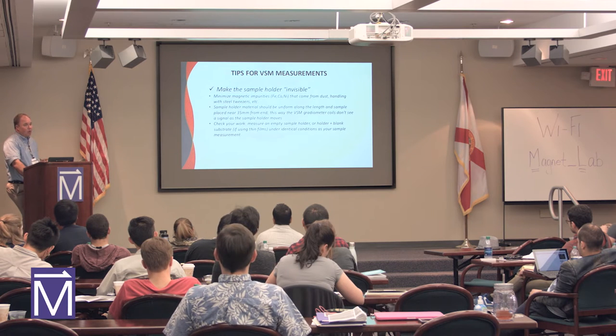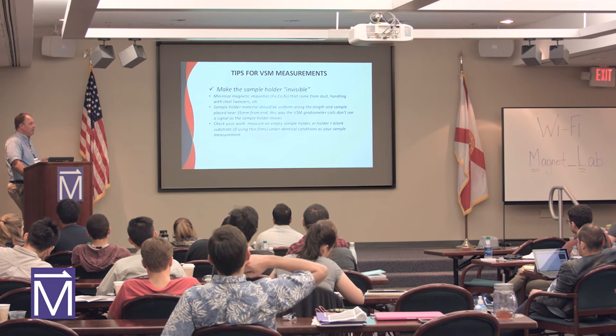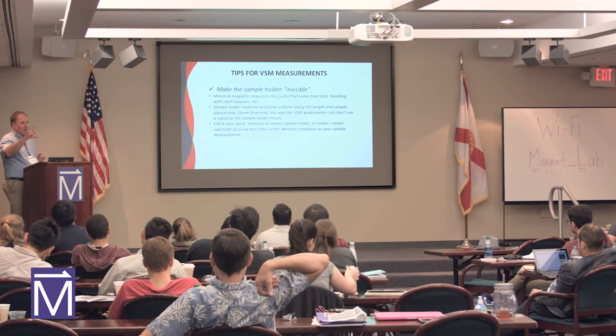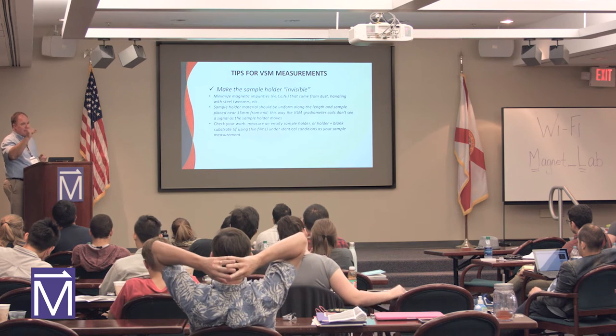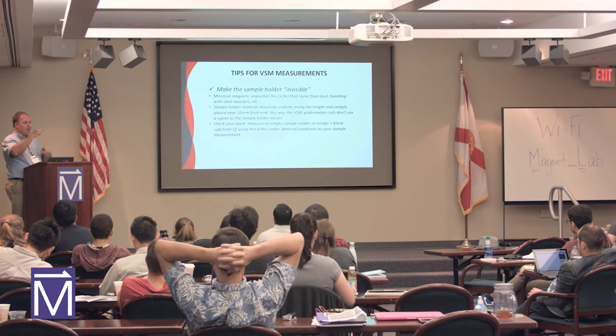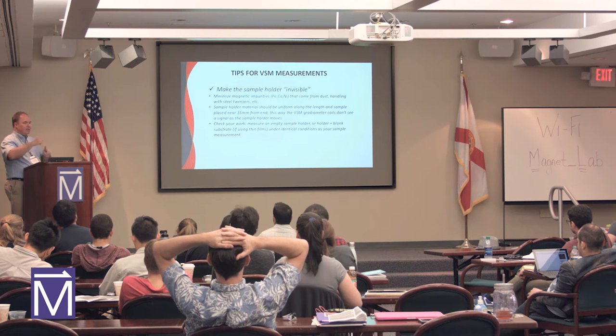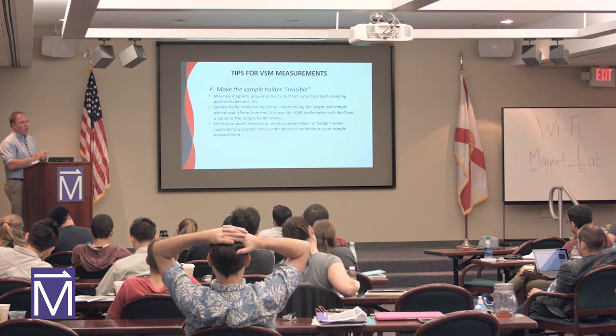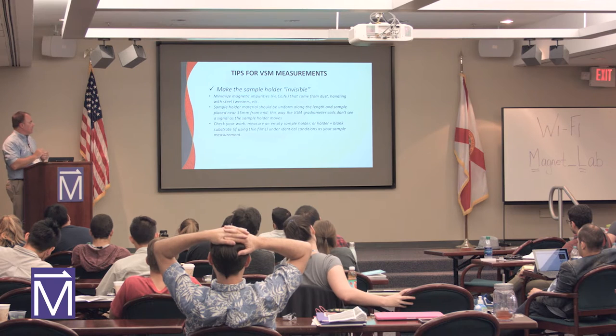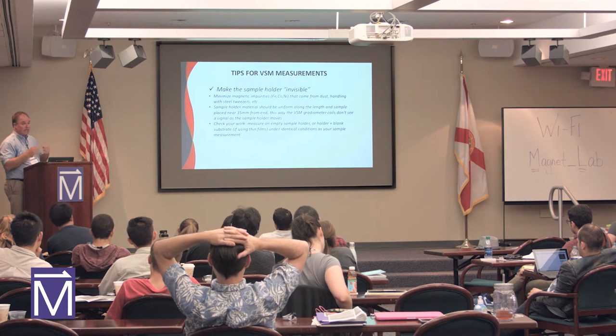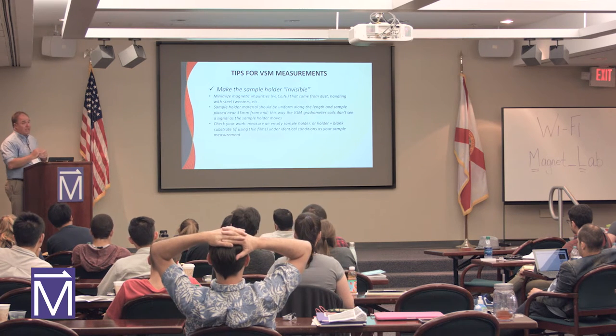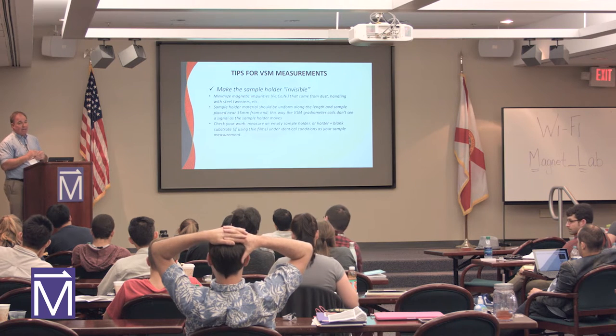Keep your sample holder uniform. The sample holder itself is long. You say, well, why don't you just make the sample holder small and put it in there? Because you want the sample holder to be constant as it's going through the coil set, so the sample holder isn't inducing anything into the coil set. So your sample holder material should be non-magnetic.